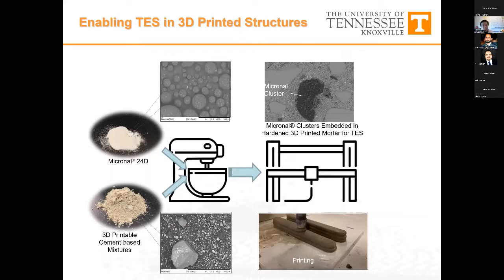So one of the initial things that we want to try here is, if we add those functional additives into 3D printable cementitious material, how that will impact printability, for example buildability and so forth, and also the hardened property of the material. So the approach that we take here, we took a functional additive. In this case, it's a Micronal powder.